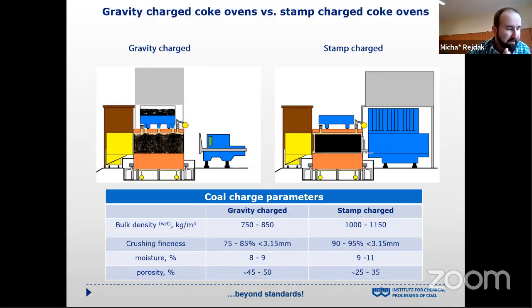We can observe that in both cases, we obtain different parameters of the coal charge for coking. Thanks to the stamping process, we obtain a much higher bulk density of coal charge, which enables the production of better quality coke or production of coke of the same quality, but with use of weaker and cheaper coals in coking blend, sometimes even non-coking coals. But the use of stamp charge technology requires a deeper grinding and higher moisture content of the coals to ensure proper stability, mechanical strength of prepared coal cake.